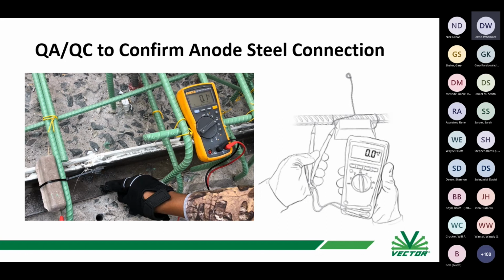So, yeah. And when you use stainless steel versus copper, for instance, is it cheaper? No, you use stainless steel instead of copper because you want to minimize having a dissimilar metal. So the type of stainless that's in those wires is, I mean, if you want a metallurgy class, a very low grade of stainless steel, and the potential difference between that type of steel and normal black steel in chloride-free concrete is virtually zero.